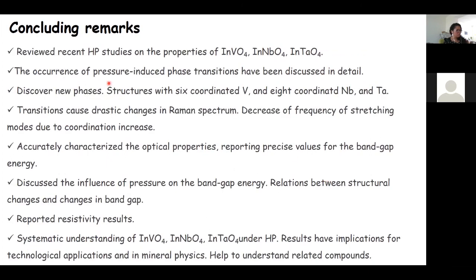So just to conclude, I have reviewed today recent high pressure studies we have done on the properties of indium vanadate, indium niobate, and indium tantalate. I have presented evidence of the occurrence of pressure-induced phase transitions, which have been discussed in detail. We have identified the crystal structure of the high pressure phase in all the studied compounds. We have discovered new phases. Indeed, the crystal structure of the new phases has been uploaded to and validated at the ICSD. The high pressure structure of indium vanadate has vanadium 6 coordinated. The ones of indium niobate and indium tantalate have niobium and tantalum 8 coordinated.